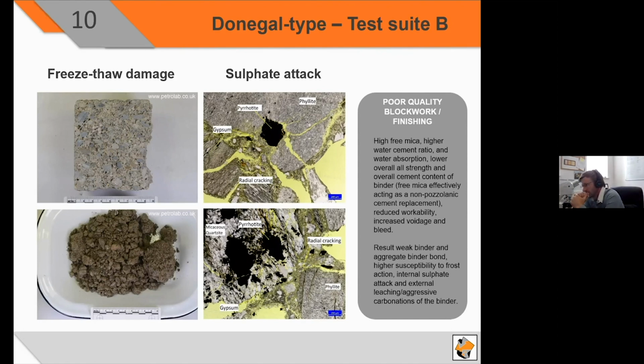One of the other key mechanisms noted in County Donegal free mica types is another form of internal sulfate attack relating to pyrrhotite. This is not currently covered by the S465 standard down the free mica route, but it's something that's been increasingly noted as a cause of critical samples within the Donegal area. In this case, like in the pyrite examples, internal sulfate attack instigates, leading to the formation of gypsum, forcing aggregate particles apart. Pyrrhotite being considerably more susceptible to oxidation than pyrite.